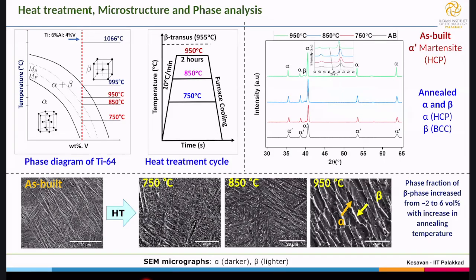So we are keeping the temperature very close to the beta transition temperature, which is about 955. If we go to 950, even 950 is not working for us, right? If we go lower, to 850, it is working. If I keep decreasing it, what happens? I will not be able to convert the alpha prime, which is HCP martensite, into alpha plus beta. That will be an issue. So I cannot go very close to the beta transition temperature, and at the same time I cannot keep a very low temperature, because I will not be able to convert the as-printed martensitic structure.